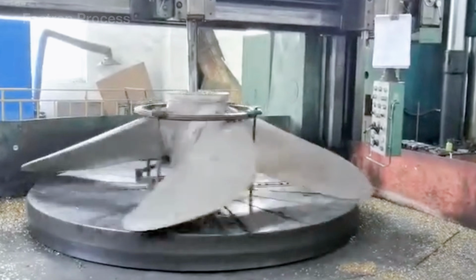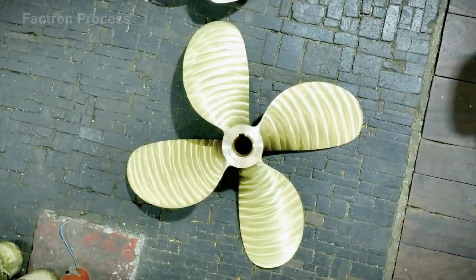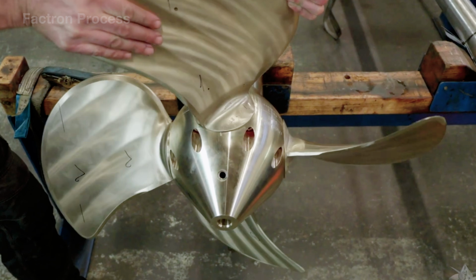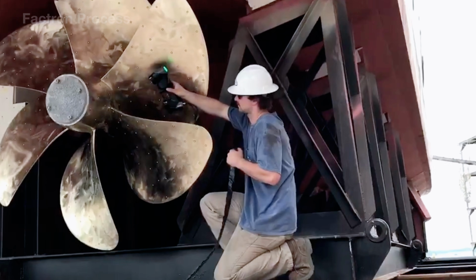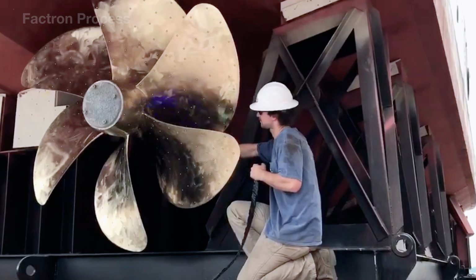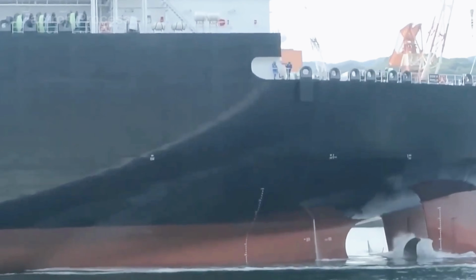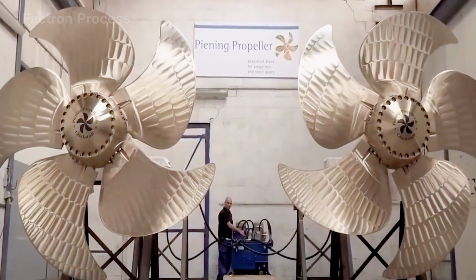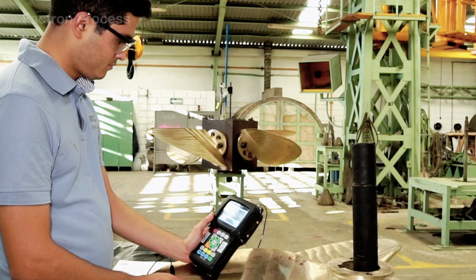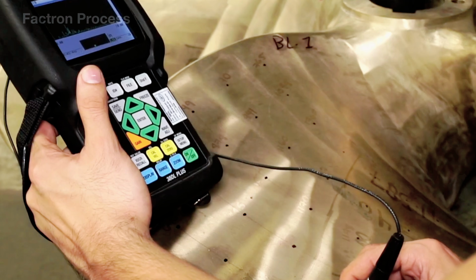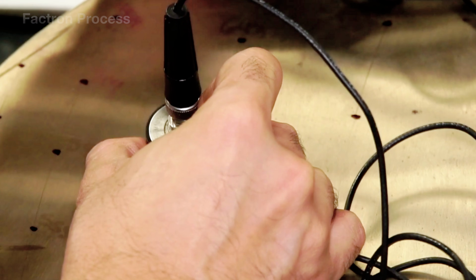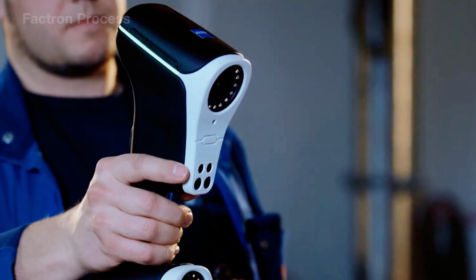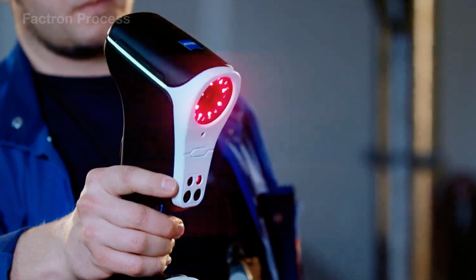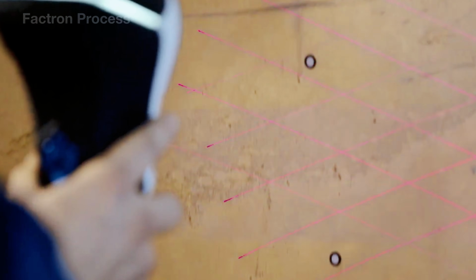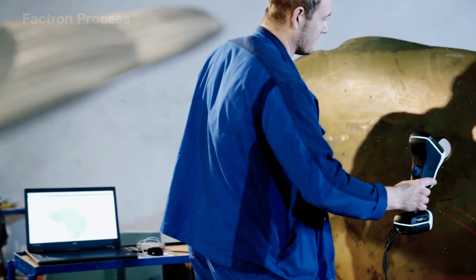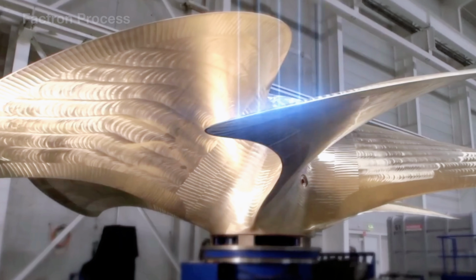A 3D laser scanner collects millions of measurement points around the blades and compares the digital model with the CAD design. Areas with incorrect thickness, angle, or twist are returned for CNC machining or grinding, while deviations at critical locations are controlled to around 0.1 mm. Next, dye penetrant enters extremely small cracks and is drawn back to the surface by developer powder, allowing engineers to detect defects. Finally, the propeller is placed on an inspection shaft to measure concentricity and weight distribution between the blades before acceptance.